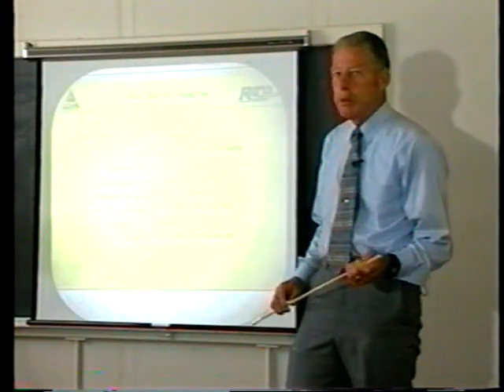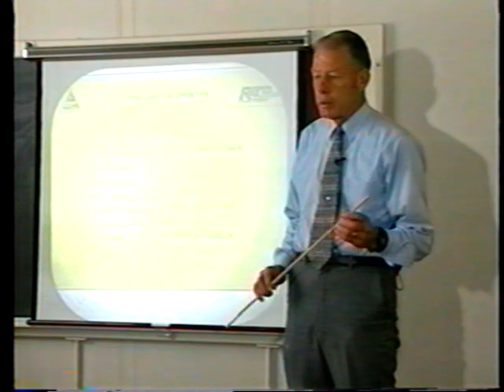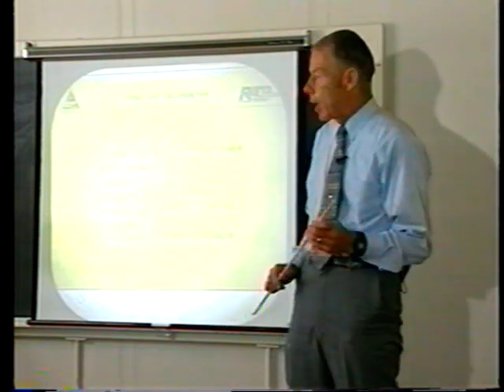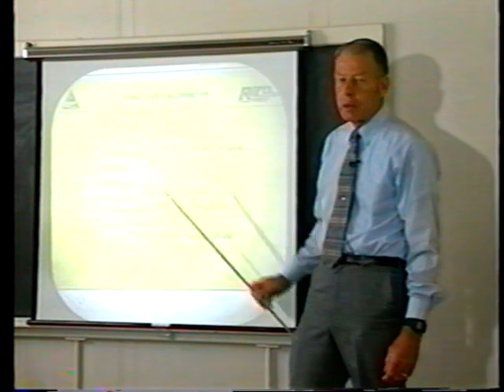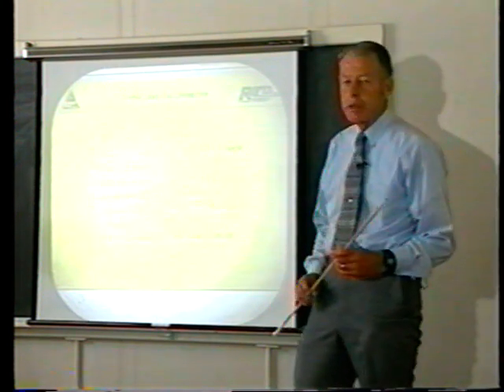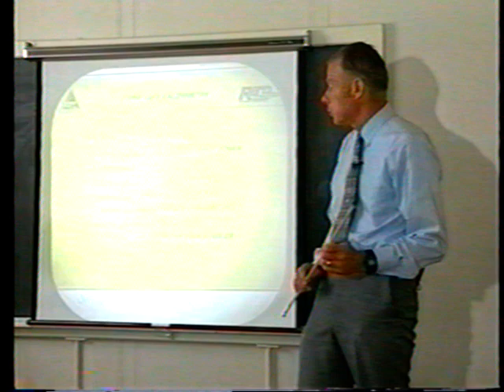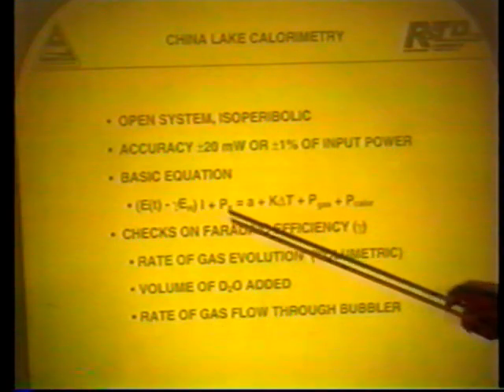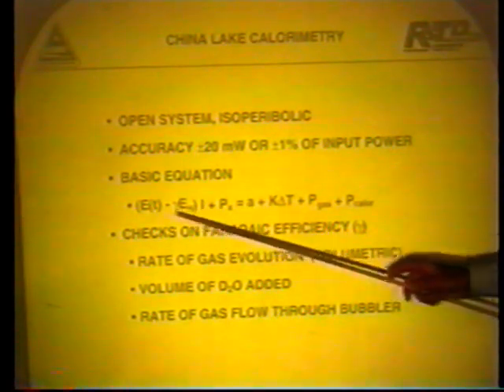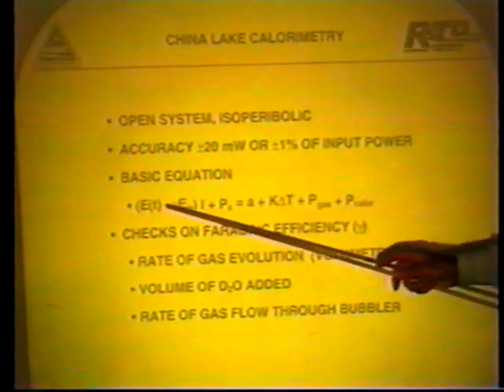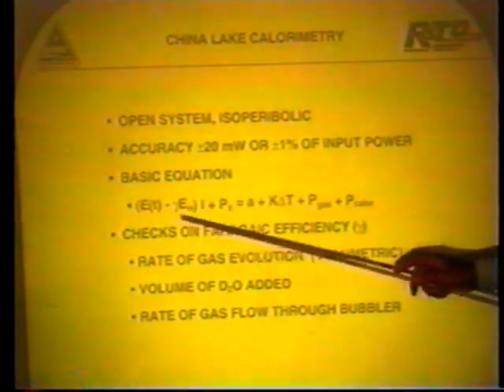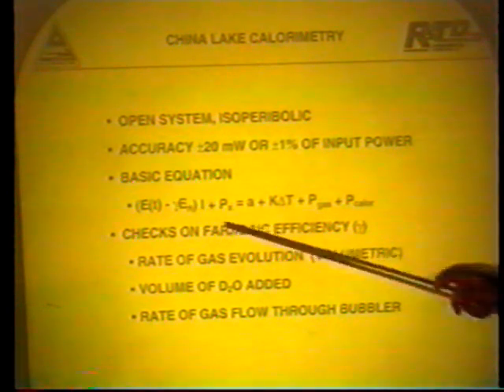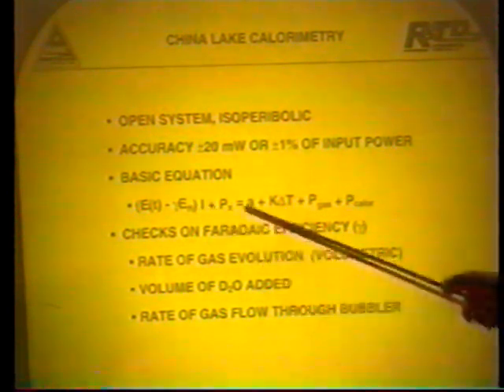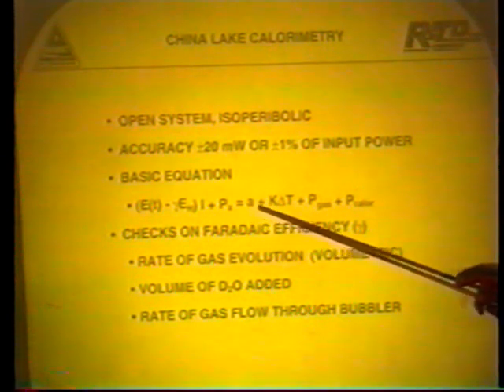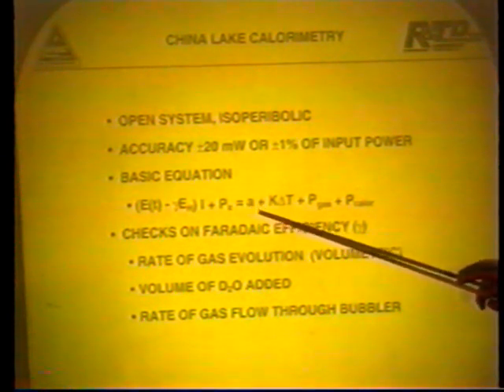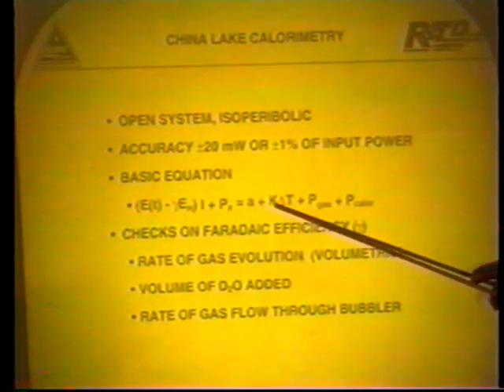The calorimetry that we used at China Lake was an open system, isoperibolic system. Our accuracy was plus or minus 20 milliwatts or plus or minus 1% of the input power, whichever turned out to be larger. Our basic equation consists of the electrochemical power in, the voltage times the current. We subtract off here the thermal neutral potential. This is the Faraday efficiency. This is the current that we used. This is the excess power, if any. This is the constant that relates to power losses out of the top of the cell. This is our calorimetric constant.